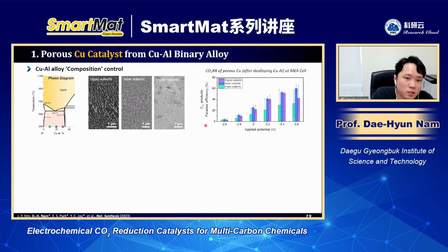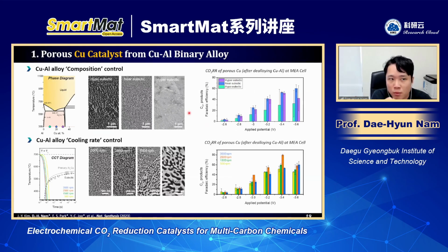At first, as I mentioned, we need to find the optimal ratio between copper and aluminum, because after the dealloying, we can have porous copper. The left-hand side shows the phase diagram between aluminum and copper, and according to their composition, we can get hypoeutectic, near-eutectic, and hyper-eutectic structures. In this way, we can have various kinds of structures. And we found that the near-eutectic one had the highest C2 products selectivity. Then we also controlled the cooling rate to get an optimal interface between copper and aluminum, which can produce the highest C2 products efficiently.